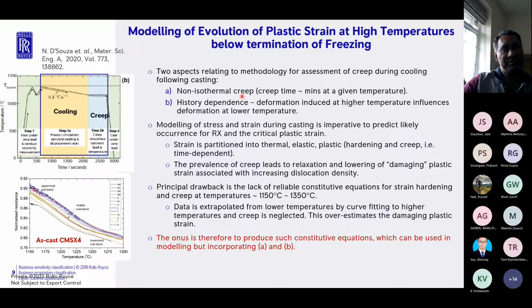The first thing is the occurrence of creep, but this is more like non-isothermal creep, because remember the material is constantly cooling. In a traditional creep test, you take your specimen, heat it to a certain temperature, and hold it at that temperature for several hundred hours. That's not the creep that we have here. In this case, the metal is constantly cooling, so at any point in time, it's only sitting at that temperature for a few seconds. So there's a non-isothermal creep aspect. The other important aspect is history dependence.